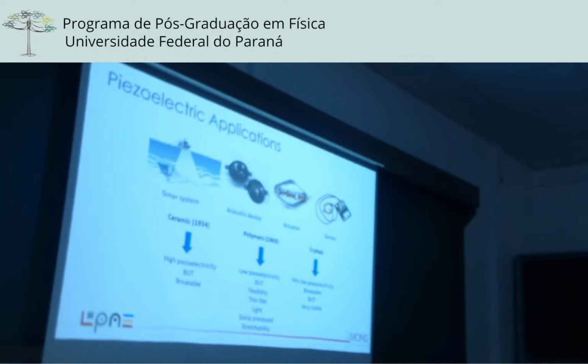For ceramics, high piezoelectricity, but they are extremely fragile. For the polymer, low piezoelectricity, but flexible, thin, light, easy to process, and stretchable. So you know why we are using polymer, for the flexibility of the device, of course. And for crystals, very low piezoelectricity, but extremely stable, which means that, for instance, for fire detectors and so on, because there is no constraint, we can use those crystals for measuring the piezoelectric or thermoelectric response, because they are stable.